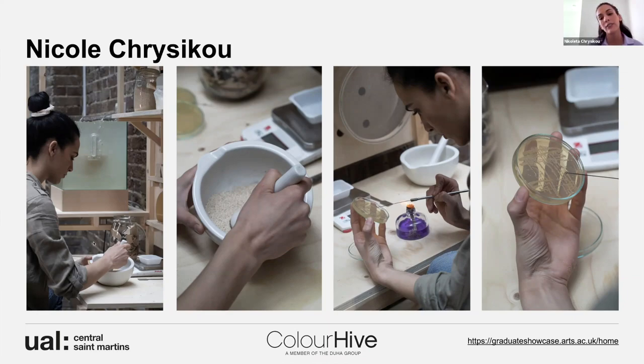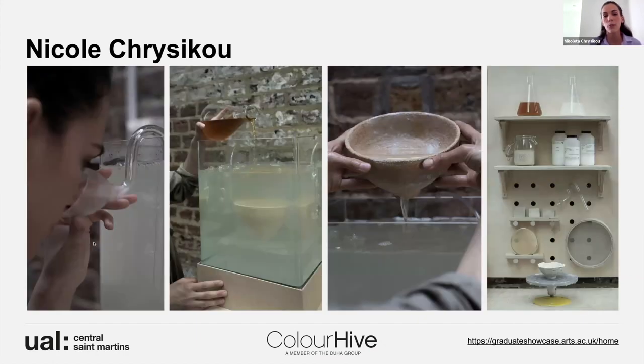And then I cultivate the bacteria. It's a soil-borne bacteria called Sporosarcina pasteurii. It's also non-pathogenic, which made it easier for me to work with. And then I put the grog, the powder, in a mold, and I add the bacteria solution and the cementation solution, which is, as I told you before, an ingredient such as calcium chloride.